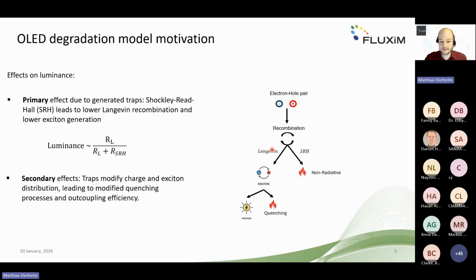about it. But in OLED, the story continues because what you care about is an exciton that forms if you have radiative recombination. And this exciton, this is a charge pair which is not separated. In the end, it leads to a radiative recombination, but it can also be quenched. It can transfer its energy, and then it's lost, so to say. It cannot recombine radiatively anymore.